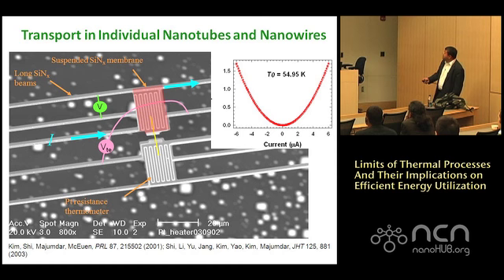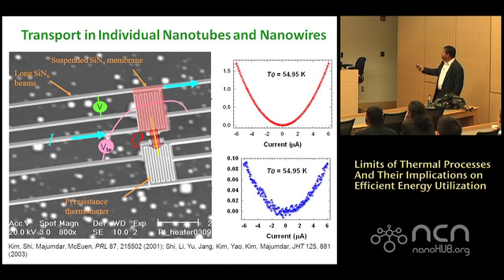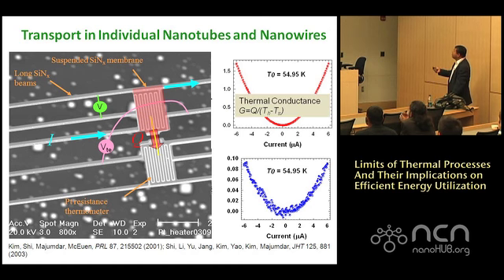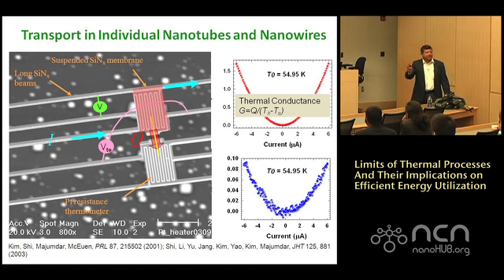You heat this, the heat flows on through this nanowire to the other side, raises its temperature. You pass a small AC current to measure the temperature of this. And this temperature difference, and also by characterizing these legs, you can find the conductance of these legs. You can actually get the total heat flow through this, the temperature difference, and you can get the conductance. And from the geometry and the conductance, you can get the thermal conductivity, you can do everything you want.